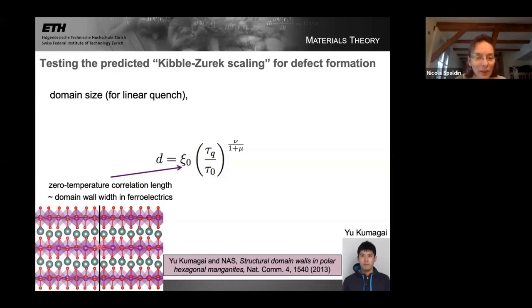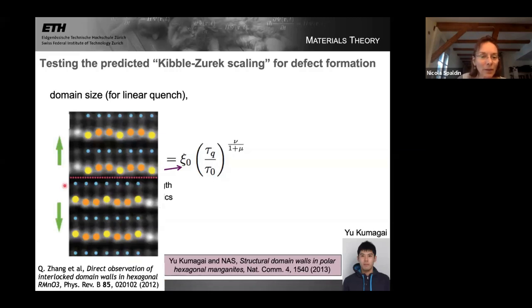I was a bit skeptical about this for some time until this was also measured using high resolution transmission electron microscopy, not by our group, but this was a really beautiful measurement, really showing that the domain wall is a very narrow plane.